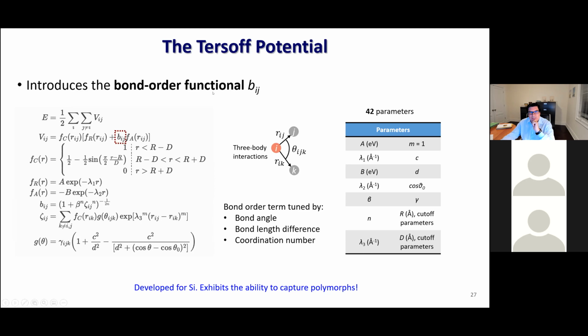of a bond order function, which is a function of a function, given here, where this function brings information about the angular dependence, the coordination, and the different lengths between, for instance, when you are sitting at one atom and you look at your neighbor atoms, and you are dealing with the ijk atoms, the distance may be different.